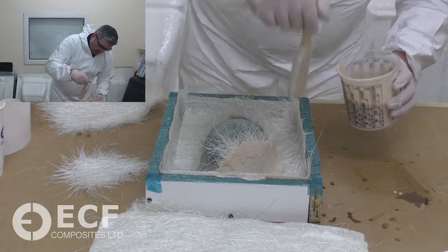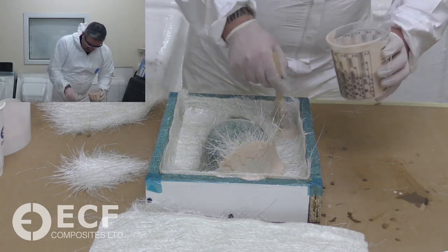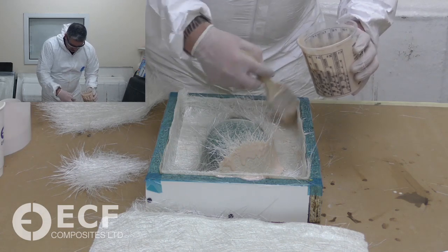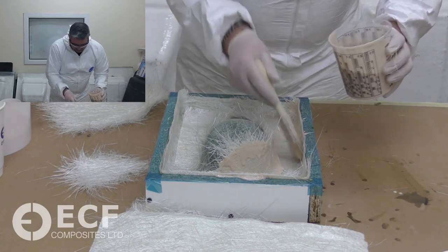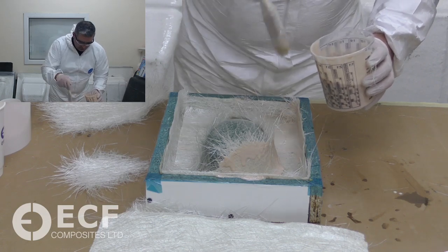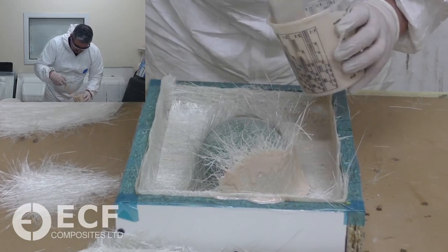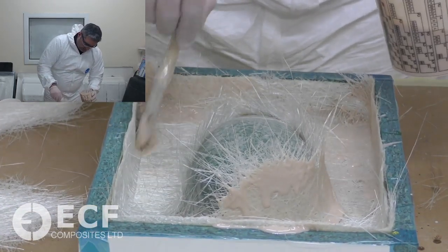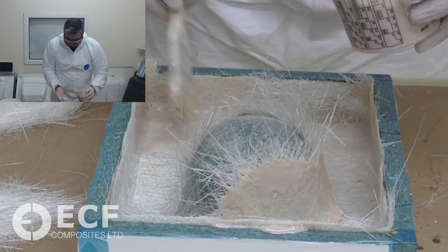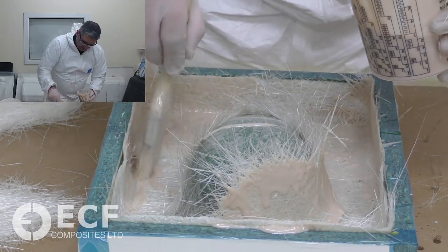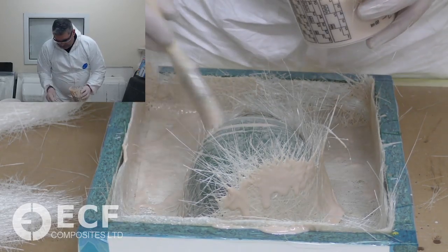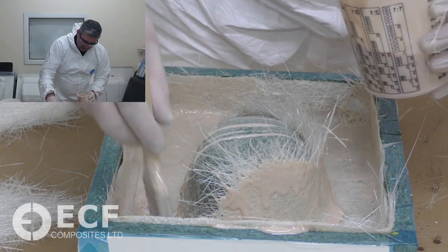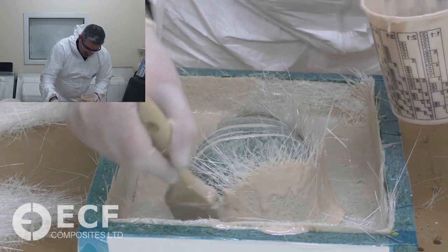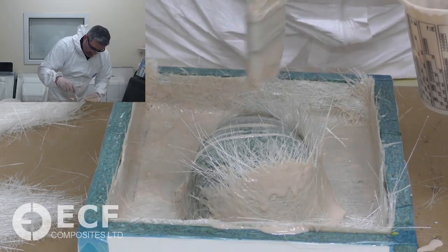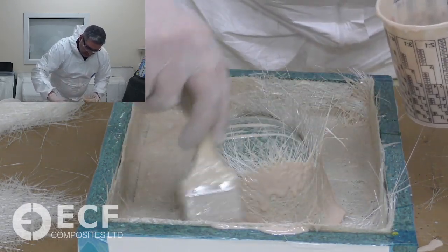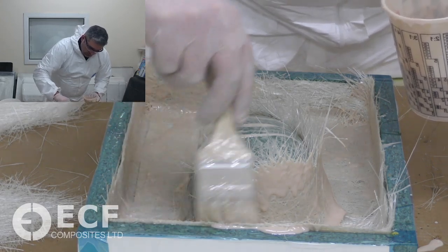See, as I'm wetting it out, I'm not spending ages on that area I've just wet out, I'm just moving on to the next area and wetting that out. I'm giving that time to break down the binder, the styrene and the resin. That starts loosening off the mat and making it more pliable, and that usually starts to happen after about 30 seconds or so - it starts to break the binder down. I'd say after about 60 seconds it really loosens the fibres and you can work it a lot easier than standing there for ages while it's breaking it down, trying to flatten everything into the corners or round areas.